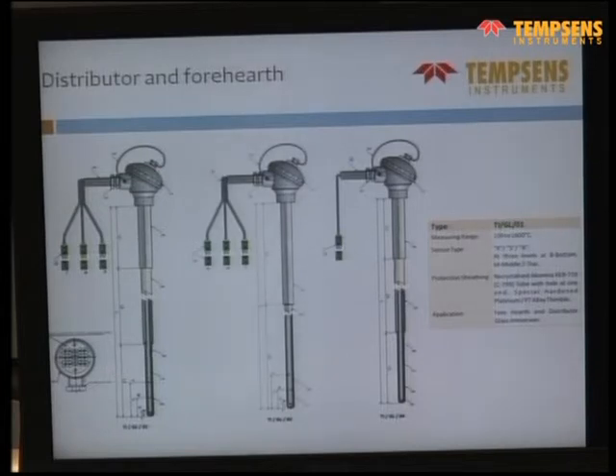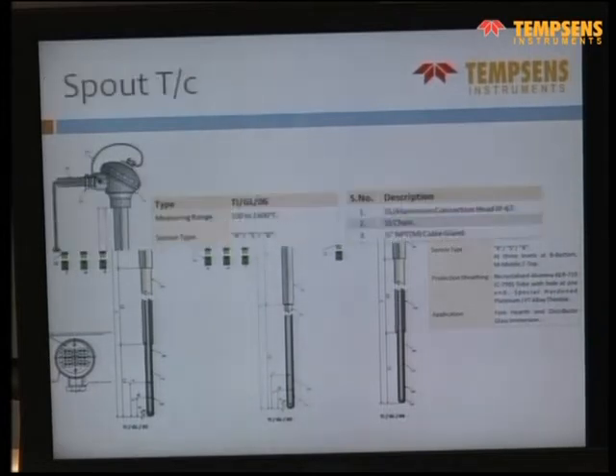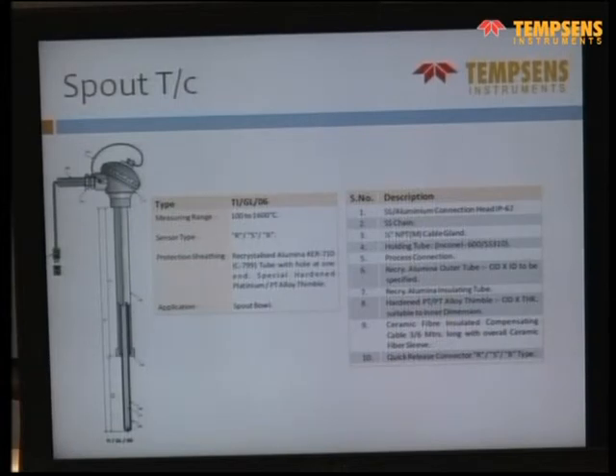Then for the distributor in forehearths, they take the temperature through the level of the glass. One is at the bottom, middle and top. So there are 3 levels of glass where the temperature is taken, and they try to homogenize the temperature through the various length as well as the depth of the glass. So it's called a tri-level sensor. Similarly, for your case also, if you want multi-level sensors, we can offer multi-level sensors. This is at the end of the glass, it's called the spout thermocouple.